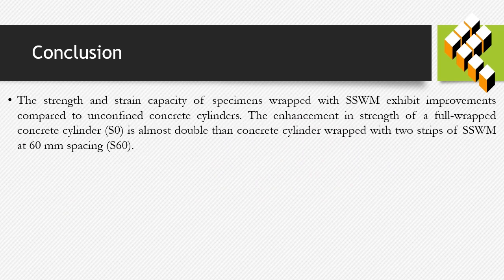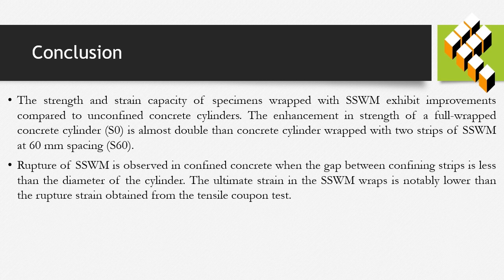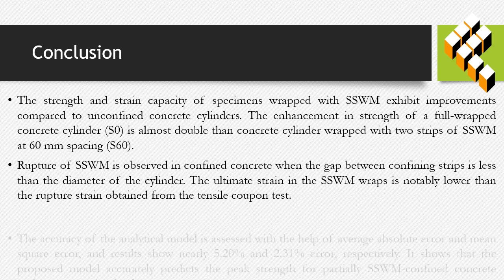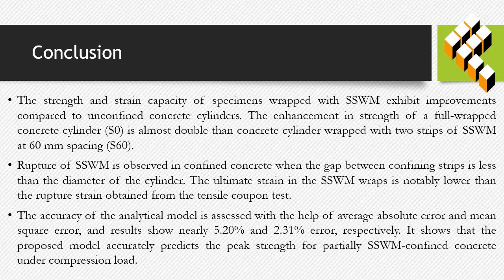The conclusion of the study. The compressive strength and the strain capacity of the specimens wrapped with SSWM exhibit improvement as compared to the unconfined concrete cylinder. The rupture of SSWM observed in the confined concrete when the gap between the SSWM strips is less than the diameter of the cylinder indicates the effectiveness of the confinement. Based on the statistical analysis, it is found that the proposed analytical model accurately predicts the peak compressive strength of partially SSWM confined concrete.